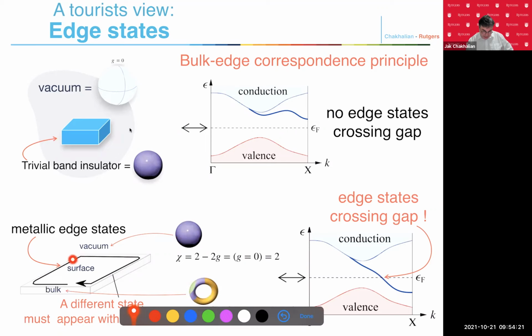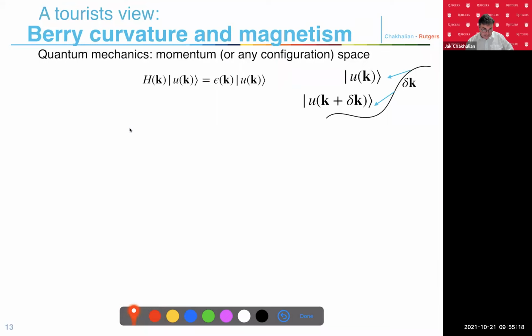So somewhere on the surface, I have to change the topological properties, because going from inside of the crystal to the vacuum requires me to punch a hole to change the genus. And that is the topological reason why on the surface I will get new states. So in other words, I have to cross the Fermi edge, I have to cross the gap, and on the surface, because I have to go between two different topological indices, I have to cross it by basically crossing the gap. And this is the reason we have surface states. So placing a topological insulator, which is the insulator with a non-trivial, non-spherical genus, non-spherical object inside, into the vacuum automatically guarantees there will be edge states. Okay, simple. That's what's called the bulk-edge correspondence. So the Berry curvature is another very important thing.